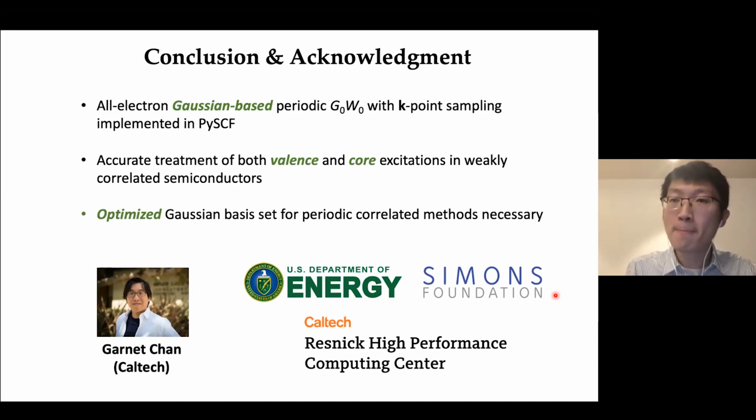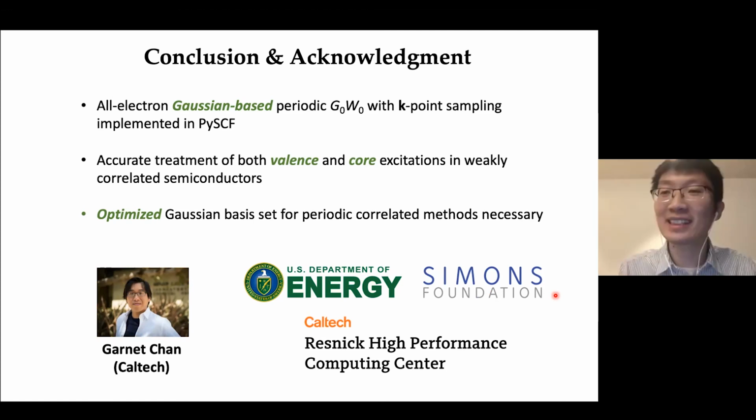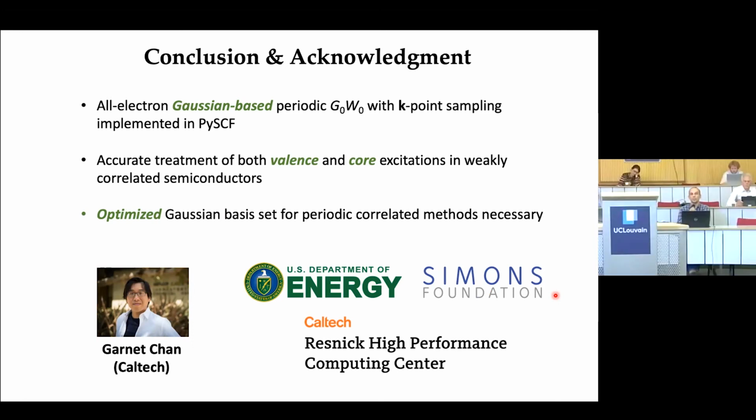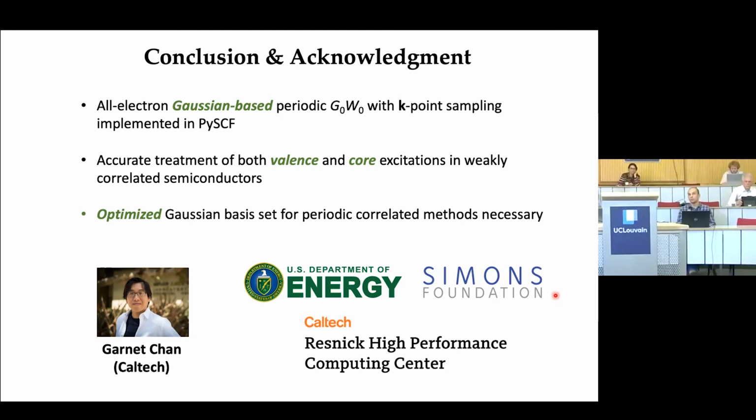In chemistry, you also have the ECP framework that are pseudopotentials, basically. Yes. And for zinc, I think you have some effective core potential that are published, and you may use this effective core potential to do pseudopotential calculations with Gaussians. And then I think this would be a more fair comparison with respect to what we do with plane waves.